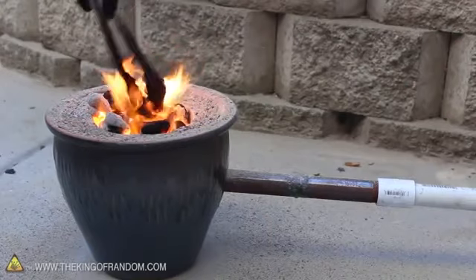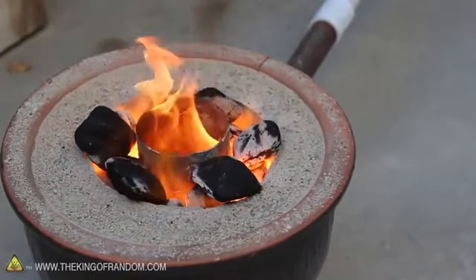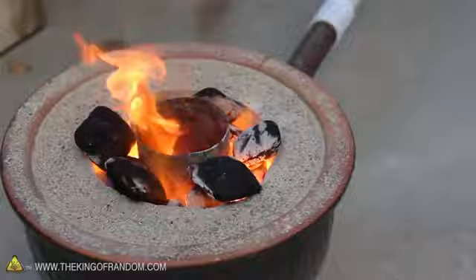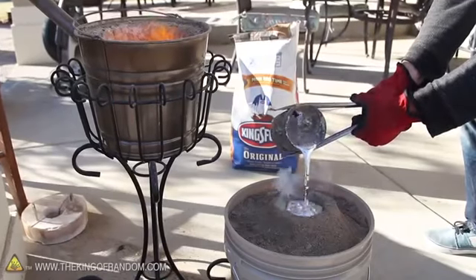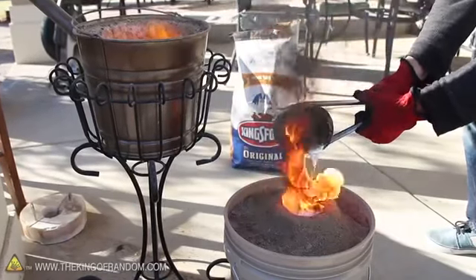Now some people wonder if you can use cement or concrete instead of plaster of Paris, and I would strongly caution you not to. The reason is if there's any moisture trapped in the concrete, then when it heats up there's the potential it could explode in your face. On the other hand, plaster of Paris and sand are very porous, so they vent the gases off, and there's very, very low risk of that happening at all.